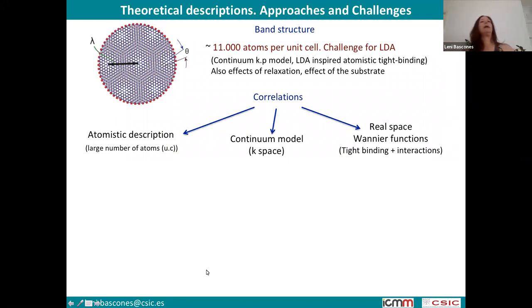Now, for the issue of how we study correlations, there are different approaches. There are people using an atomistic description, really starting from the carbon atoms, so we really have a lot of atoms. Most people, in fact, use a continuum model based on k-space, so you really have a description in k-space, not in real space. But of course, for studying many properties, and in particular if you want to study whether Mott physics is important in these systems, you would want a real-space model based on Wannier functions. Here, I mean Wannier functions for the whole moiré unit cell, not atomistic-like.